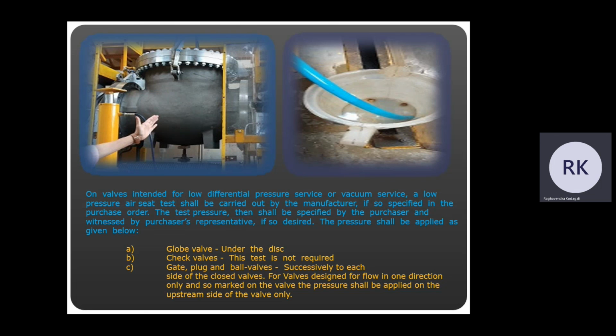On valves intended for low differential pressure service or vacuum service, a low pressure air test or air seat test shall be carried out by the manufacturer, if so specified in the purchase order. A test pressure shall then be specified by the purchaser and witnessed by the purchaser's representative. If so desired, the pressure shall be applied as follows: globe valve, under the disc; check valve, the test is not required; gate, plug and ball valves, successively to each side of the closed valve. For valves designed for flow in one direction only and so marked on the valve, pressure shall be applied on the upstream side of the valve only.